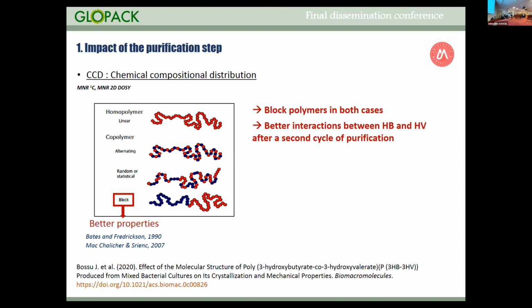And with this advanced technique, we demonstrated that we obtained block copolymers in both cases, so it was a very good point for our project, but that after a second cycle of purification, we had better interactions between the HB and the HV blocks. So all this advanced characterization demonstrated the importance of the purification step, but also of the second round of purification.